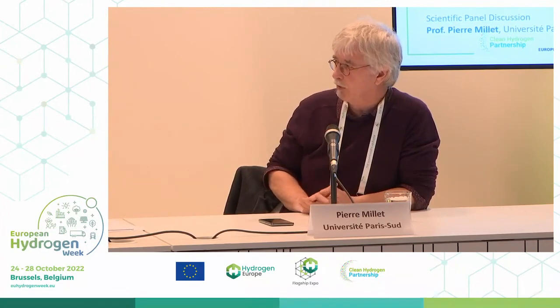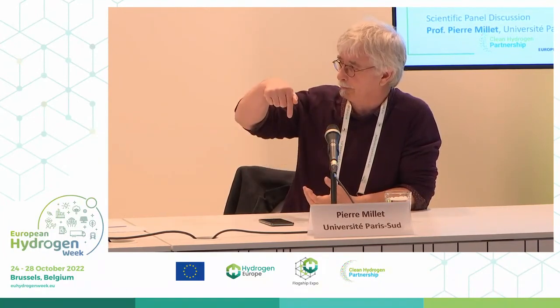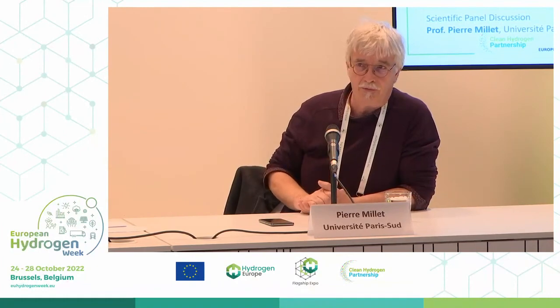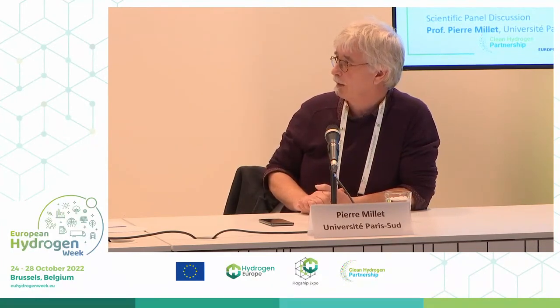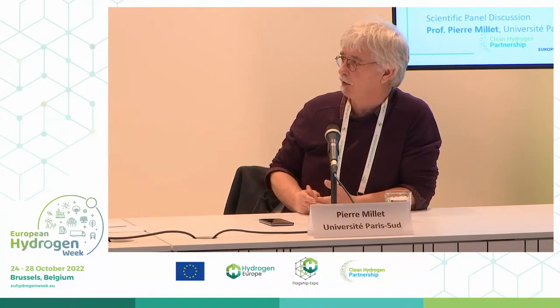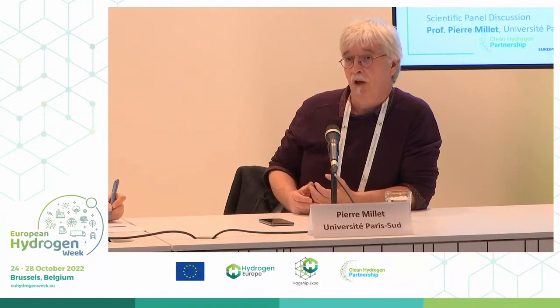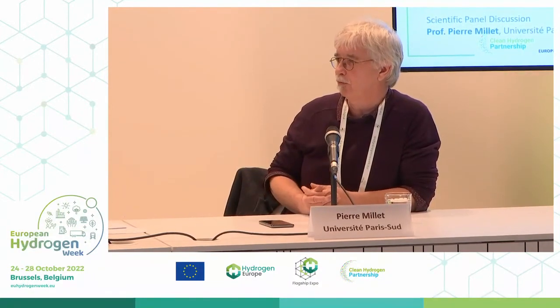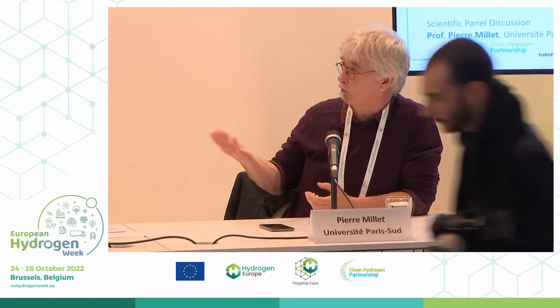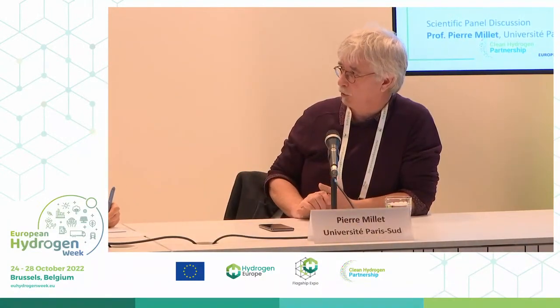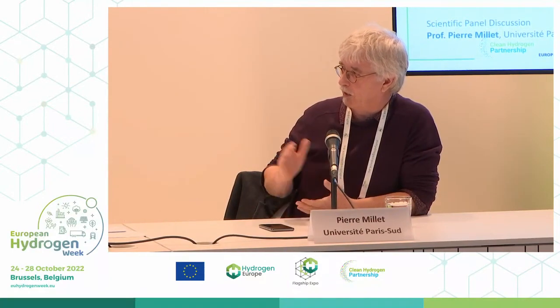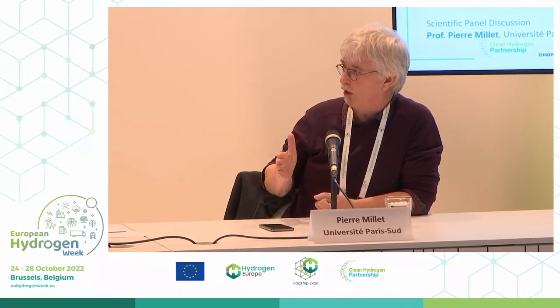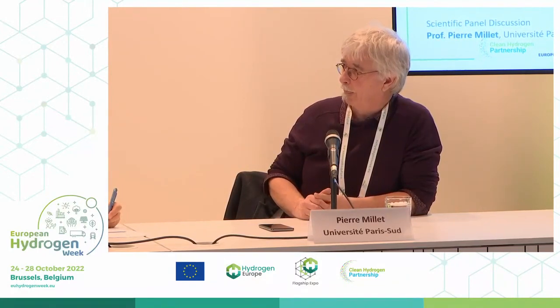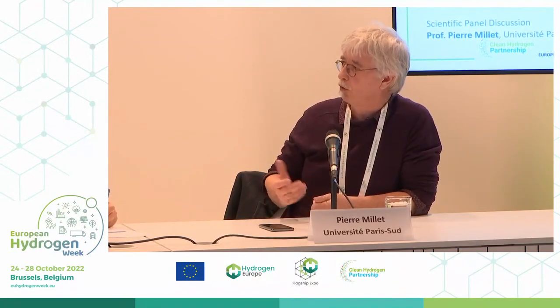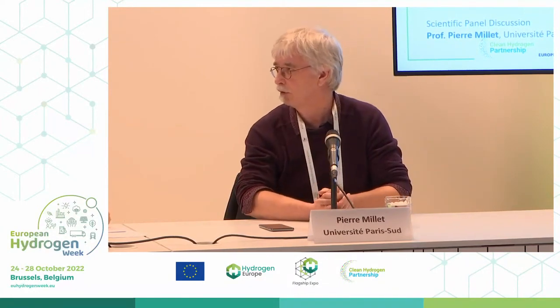But with oxygen, probably the situation is different. Adsorption can be on top of one site, and therefore, at one moment, there should be a hydroxide somewhere. And the interaction between that site and this hydroxide is probably the critical step. So to progress, of course, it is necessary to measure the turnover frequency of these materials, and to be sure that we can get rid of nanostructure and expanded surface area, and concentrate on just learning more about what's going on. But this is a general comment.